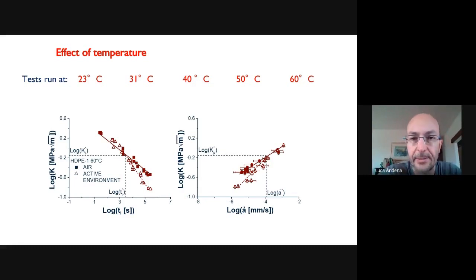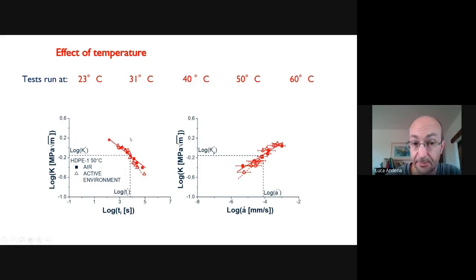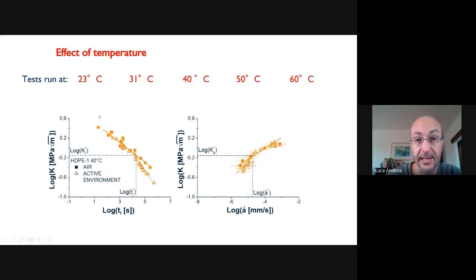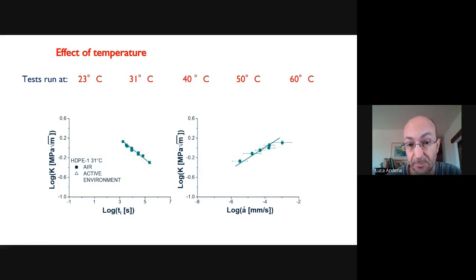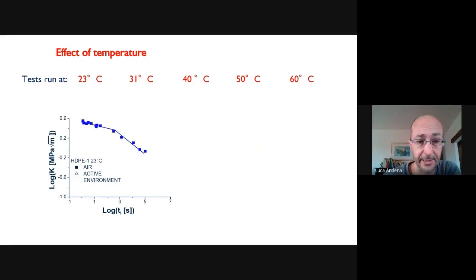In this data, I'd like to show some results on the polyethylene we've seen before, taken at different temperatures. These are the previous data. If you look at 50 degrees, you see a very similar trend, but as you increase the temperature, the curves rise a little bit, as you would expect, because things slow down, so you will need a higher K to get fracture in the same amount of time. And here is the curve at 23 degrees, in which you also see the brittle and the ductile failure region.